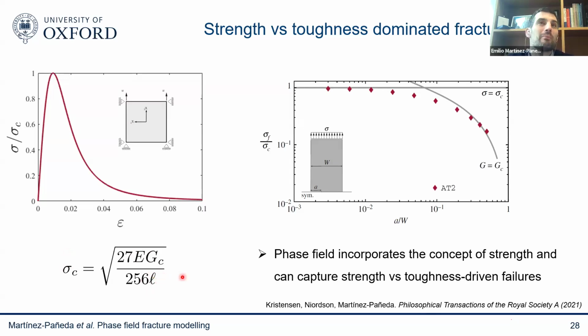So the length scale has a physical meaning. It basically tells you, it's an indication, it's proportional to the fracture process zone of the material, which makes sense, of course. Every time we talk about a fracture toughness, we bring in a fracture process zone idea. So we need to be able to resolve the fracture process zone, and that will be, of course, a material property. Different materials have different sizes of fracture process zone. So basically, by picking your length scale, you are picking the strength of your material. So this means that the two parameters that we need are either the toughness and the strength, or toughness and length scale. They are the same.